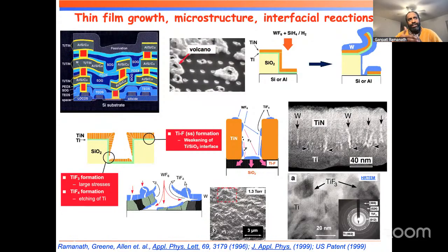So after preparation for nearly about 3.5 years, learning many skills and publishing many papers, I did my PhD thesis really in about 6 to 7 months. So what we found really was that the titanium nitride layer, which is on the left side, which is written TiN over here, that is porous, and the tungsten hexafluoride was going through it, and that caused reactions, which gave rise to essentially TiF3 formation, TiF4 formation, which broke up these layers.